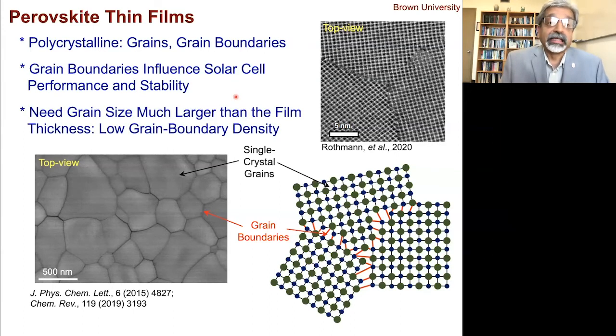And therefore, what we need is grain size, which is much larger than the thickness of the film. And that is basically a requirement. So it reduces the density of these grain boundaries and increases performance and stability. I'll give you one example.